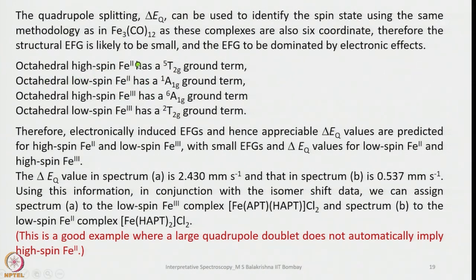four cases. Octahedral high spin Fe2+ has a 5T2g ground term, octahedral low spin Fe2+ has a 1A1g ground term, octahedral high spin Fe3+ has a 6A1g ground term, and octahedral low spin Fe3+ has a 2T2g ground term. Therefore, electronically induced EFGs, and hence appreciable ΔEQ values, are predicted for high spin Fe2+ and low spin Fe3+, with small EFGs and ΔEQ values for low spin Fe2+ and high spin Fe3+.